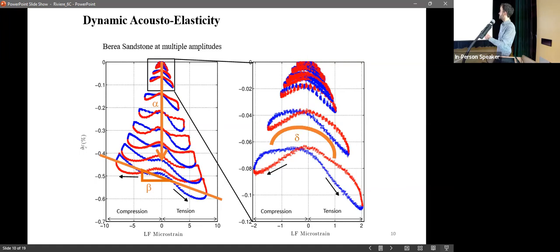So at intermediate strain, this is the plot on the right. This is just a zoom in of what we see here at the top. We see that velocity is actually lower in tension and also lower in compression. So when we see this, we're like, what's happening? Why is the velocity lower in compression as well? We think this is related to the shearing of the cracks or shearing of the grain contacts. Every time you shear in one direction, velocity is lower. You shear in the other direction, velocity is lower, and then you go through a maximum when the strain is 0. So this is our intuition of what's happening.